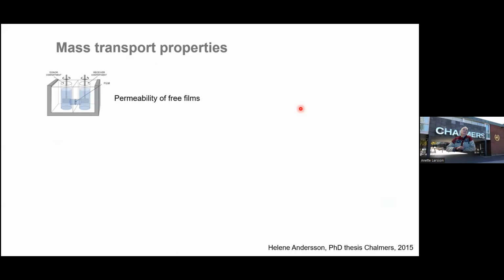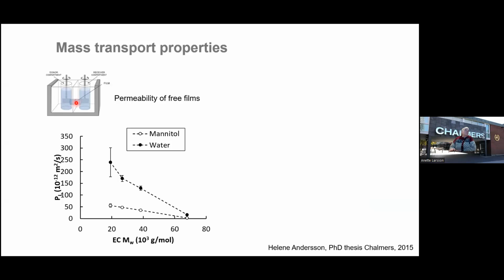So one way to study the effects of this is to use a side-by-side diffusion cell, where you have a donor and an acceptor, and in between you place the free films. And we then add radioactive labeled water here and look at how fast the radioactive labeled water is transported to this side. That we use tritium labeled water is very good, because then we create the same osmotic pressure on both sides. So it is actually the diffusion process we are looking into. And here we have the water, and we did the same for mannitol, and you can see the permeability for one particular film here is higher for water than mannitol. But also that when we increase the molecular weight of the EC phase, then we get a lower and lower permeability through the film.